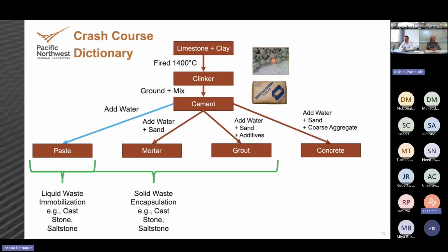So if we're D&Ding a facility and you wanted to fill out into a void space, something that looks like a grout that will run and flow, likely used. And then concretes are things that look a lot like what we've used in void filling or in tank closure at other sites. So mainly the tank closure they've done at Savannah River site, those materials are very, very similar to concretes. Conventional concretes, although tailored to be far more flowable and have ideal set times. And if you are filling a 1 million gallon tank, you can continually operate and get a resulting product, but it looks a lot like concrete. Okay.